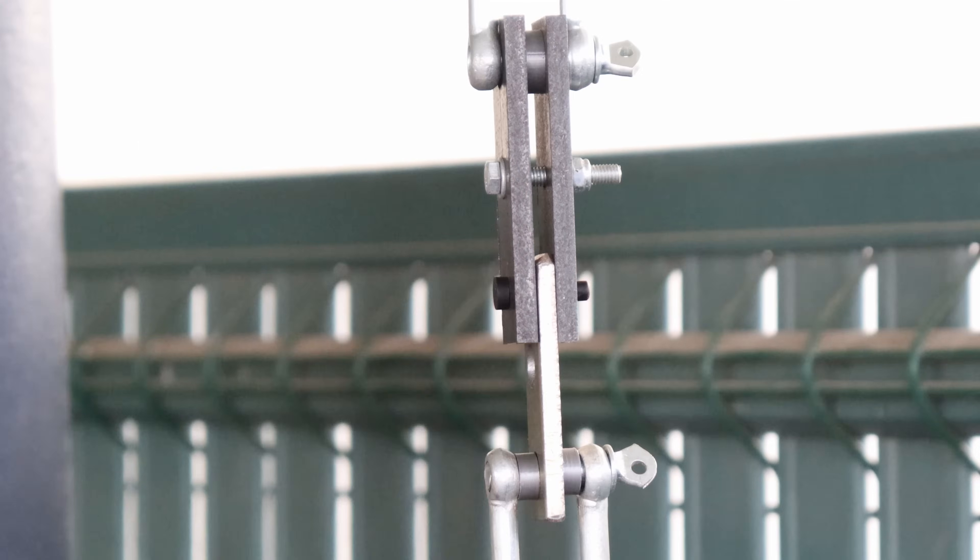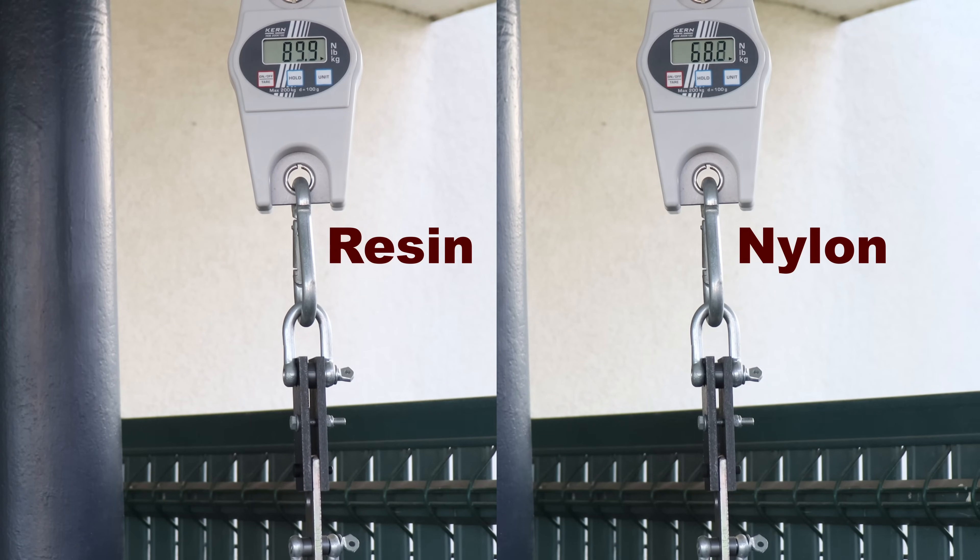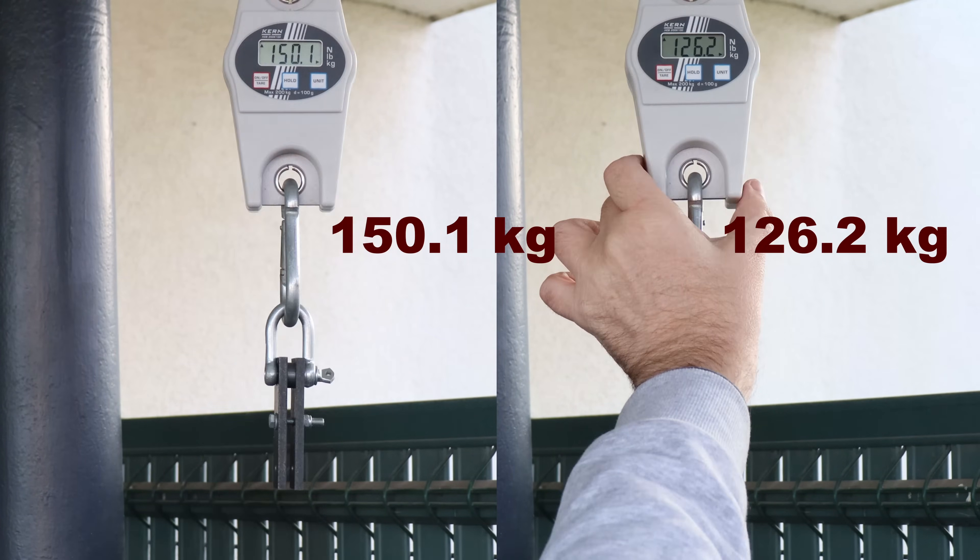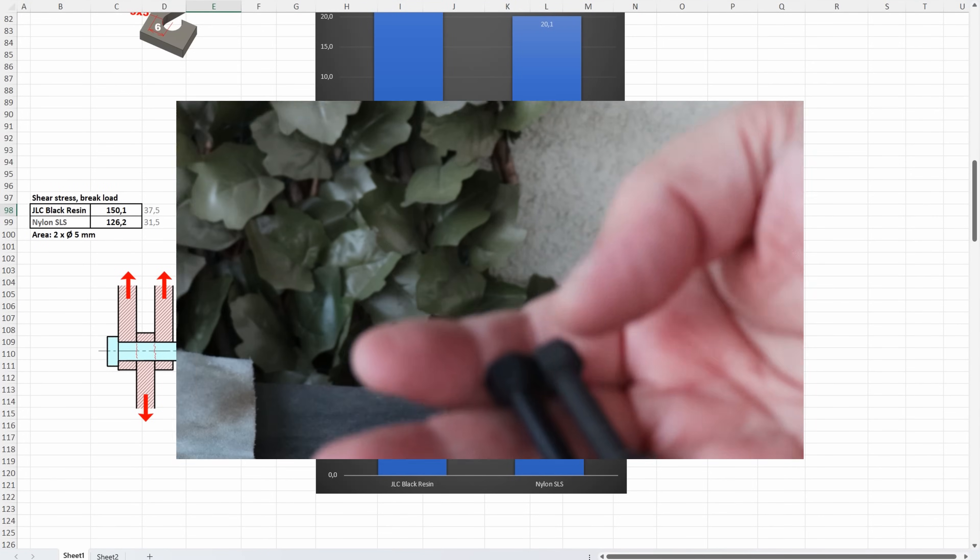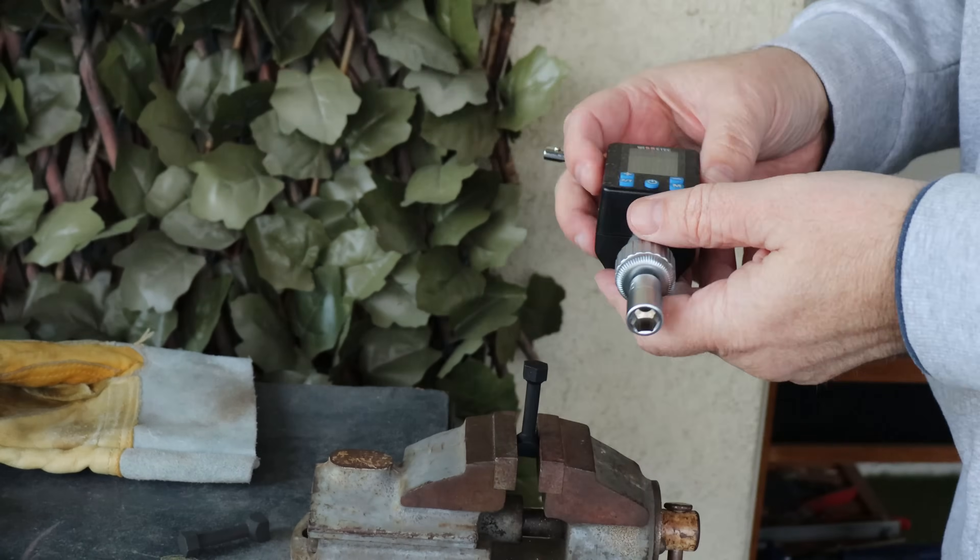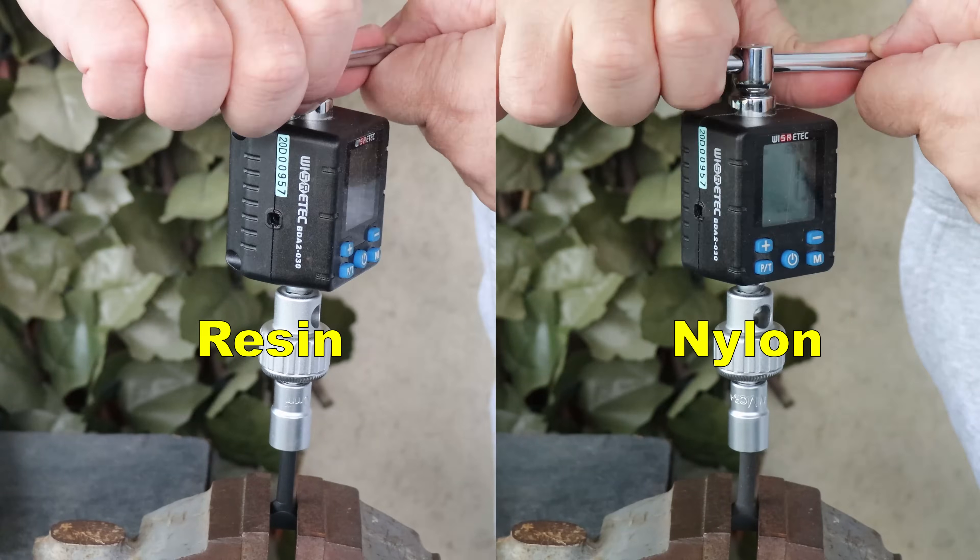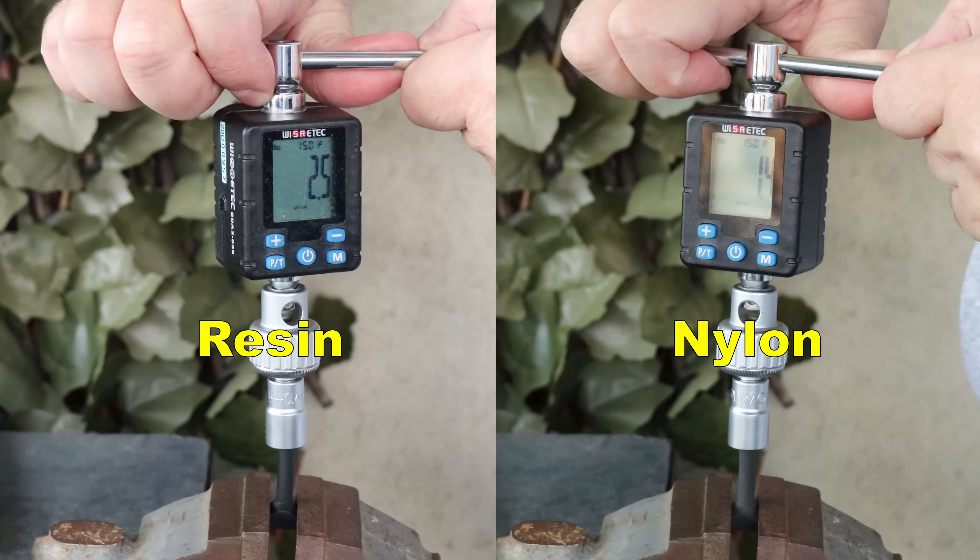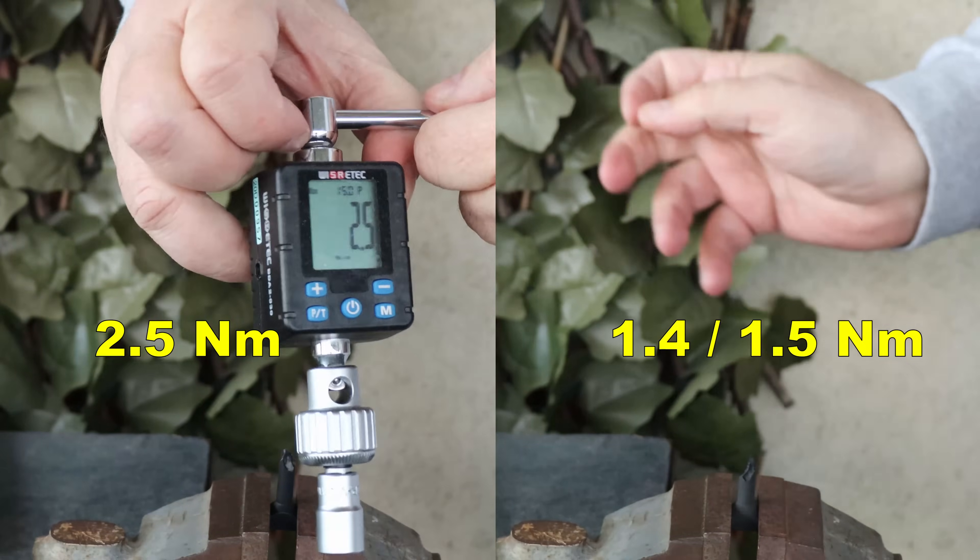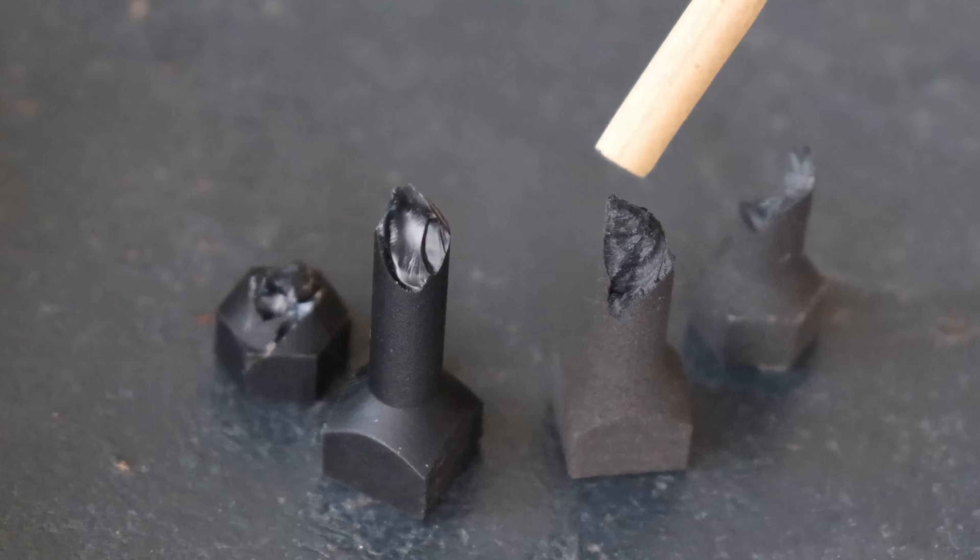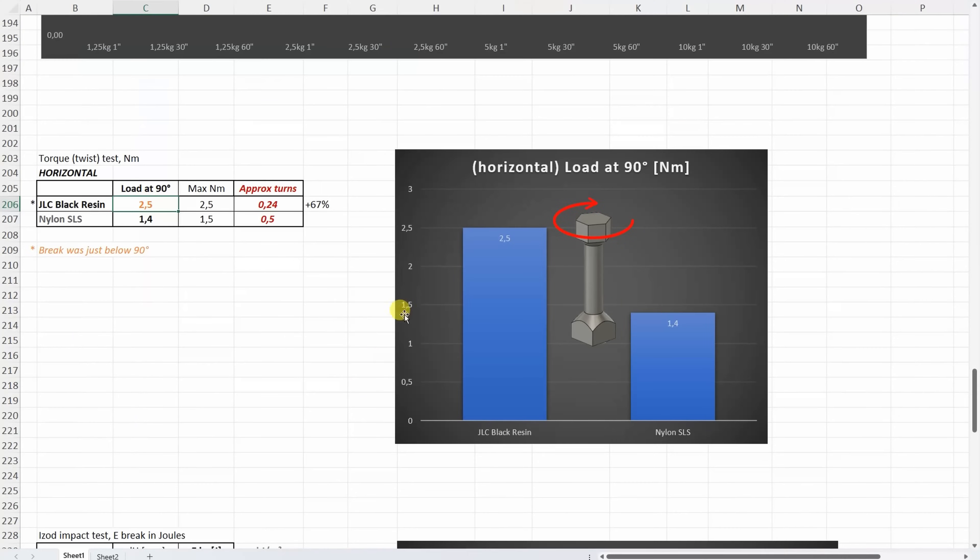Two sided shear test, the diameter is 5 mm, side by side two materials, quite big break loads. On a shear test the resin was stronger again but this time only by 19%. The torque or twist test diameter is 6 mm here and I'll try to record the load at 90 degree rotation and the maximum load. Very interesting break cross section surfaces and also very sharp in both cases. On torque or twist test the resin was stronger compared to the nylon by approximately 67%, only I couldn't make 90 degree rotation with it but this is not a bad property especially if we need some stiffness.